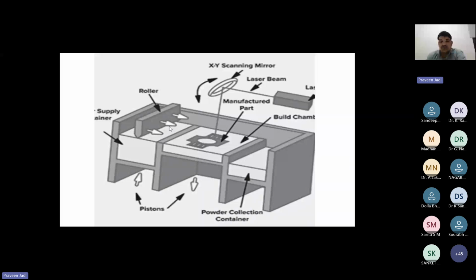Here we are using 100% metal powder without sieving, and it is in an argon atmosphere, because when the laser falls on the material, there are chances of fire inside the chamber. So we supply argon to the chamber. Argon is non-reactive, so whatever fire or spatter is happening, it won't react. That is the reason we are using argon, or we can use nitrogen gas also. So it depends on the material.